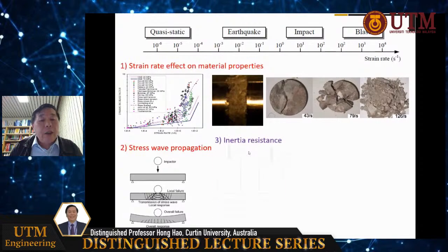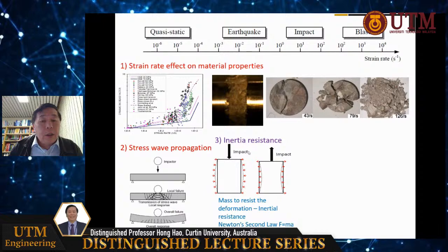And the third reason is the inertia resistance or inertia effect. Let me give you this very simple example. You have a sample there, subject to, say, uniaxial compression or tension. The structure will deform laterally due to the Poisson's ratio effect. Under static loading, no problem, it just deforms laterally. But under very fast impact loading, the deformation is very fast. That means you have a very big acceleration. This acceleration, according to Newton's second law, will induce confinement, which will prevent this kind of deformation.